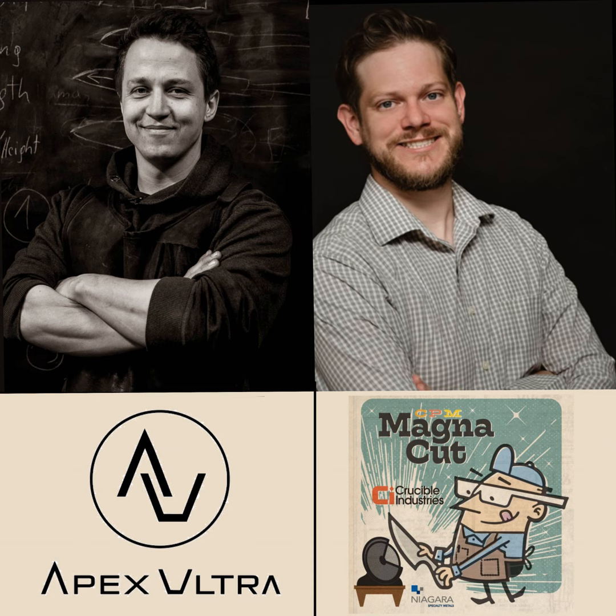Keith, do you have another question? Just in regards to the warping issue, as soon as you start with some kind of a laminate, all the effects have to do with the outside jacket material that you're using. Yes, especially if you're using something that's not a hardenable steel. So I would always say, if you have Apex Ultra in the core and ADCRV on the outside, they behave somewhat similarly, so you can do anything with them. You can basically treat them as a mono steel during forging, during heat treatment, and so on. You just need to make sure you grind until your Apex Ultra is in the middle. And you can even do cryo treatments, because the two steels behave very, very similar.